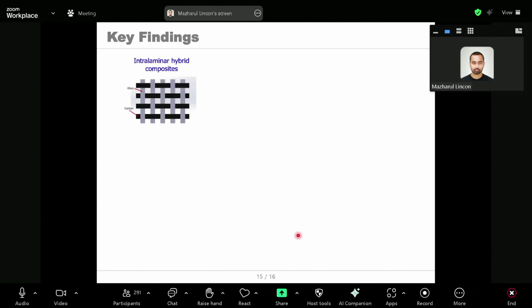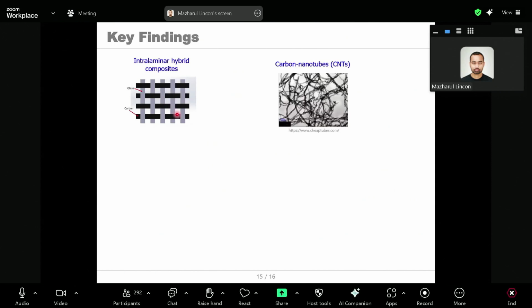In this research, we use intralaminar hybrid composites. The main advantage of this composite is we don't need to use carbon nanotube to make it conductive. We can use this composite directly in any damage sensing structure, and in any structure to analyze damage sensing capability and do structural health monitoring. Carbon nanotube is very hard to disperse uniformly in resin, making it difficult to create a uniform conductive specimen. But with this composite, you don't need carbon nanotube—the composite itself can create a good conductive network, useful for structural health monitoring.